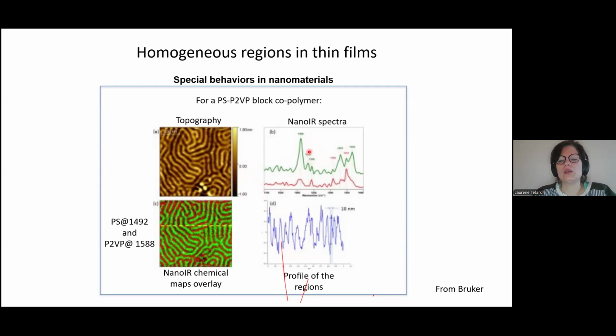And then you could select a band, fix the laser illumination at one band, and map to see which polymer is where by selecting bands. For instance, if you select this band, it's only present in the green. So when you excite the sample at this wavelength, wherever you have a high signature, that means this is the polymer that corresponds to the green here that is present. So that's more for trying to figure out that everything works fine. And it also has a lot of use in polymer science.